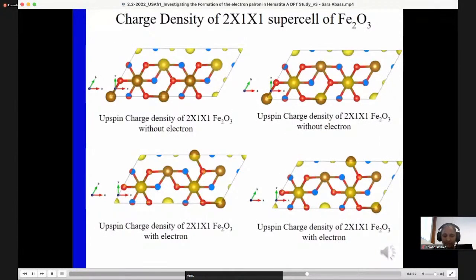And when we decide to look at the charge density of the system in the case of the 2 by 1 by 1 supercell hematite, we show the up spin charge density and down spin charge density of the system with and without an electron. We show clearly that with an electron in the system, the electron is located around an iron atom, while a part of the electron goes to some of the oxygen atoms. But this shows that some of these electrons are localized on the iron atom.